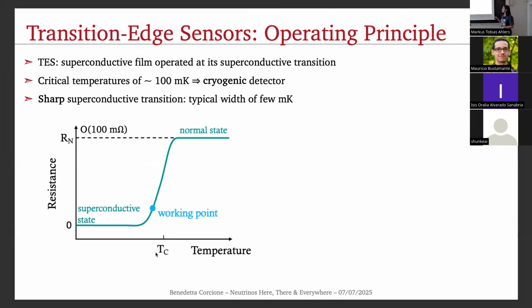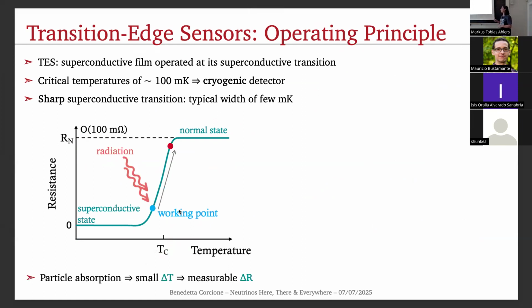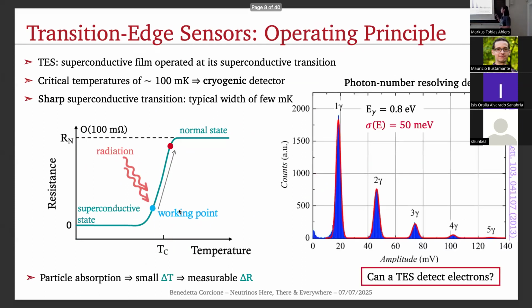So a TES is a superconductive film operated at its superconductive transition, where it is more sensitive to changes in its temperature. And when a particle arrives on a TES, it gets absorbed, so the device heats up, and even slight changes in temperature lead to measurable changes in resistance. Transition edge sensors have been traditionally used as photon number resolving detectors, as they have an astonishing energy resolution, and in particular, we can distinguish how many photons hit them simultaneously, basing on the amplitude of the signals.